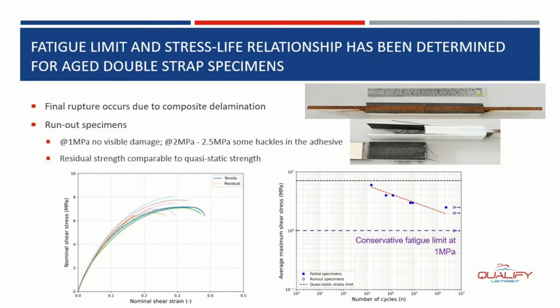At the right, you see an overview of the fatigue tests. At the horizontal axis, the number of cycles that were survived for a certain maximum shear stress at the vertical axis. So the blue full circles indicate failures where the specimens really reached rupture. At the bottom, near the horizontal dashed line and a little bit above, you see a few circles which are open and with an arrow to the right. These indicate specimens that did not fail at all. So we reached 5 million cycles of fatigue without failure.